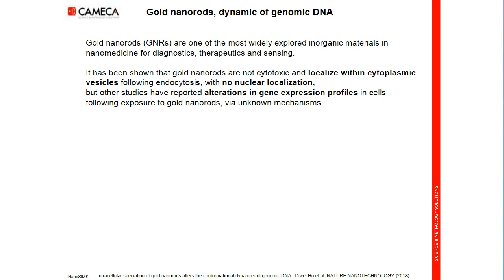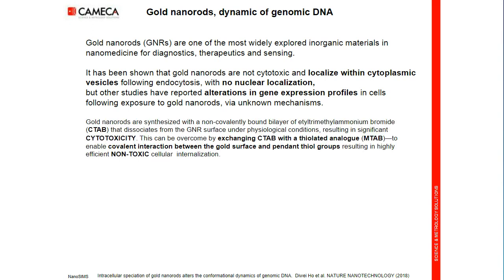So, a small detail on the fabrication of gold nanorods. If the gold nanorods are synthesized with a non-covalently bound bilayer of CTAB, CTAB will dissociate from the gold nanorod surface under physiological conditions, resulting in significant cytotoxicity. This can be overcome by exchanging CTAB with a thiolated analog, MTAB, to enable covalent interaction between the gold surface and pendant thiol groups, resulting in highly efficient non-toxic cellular internalization.